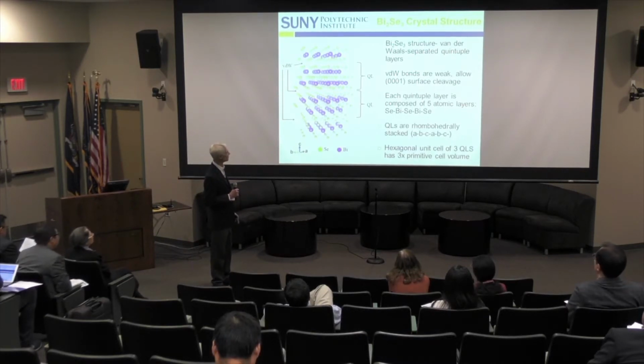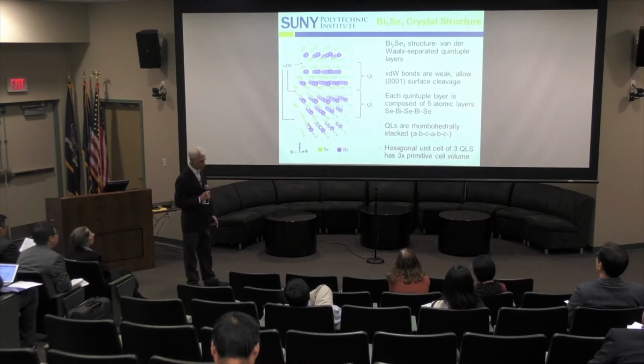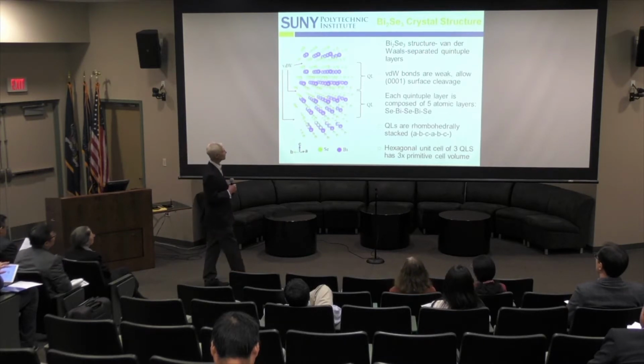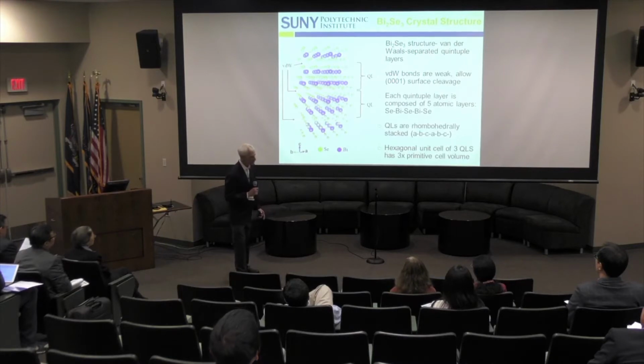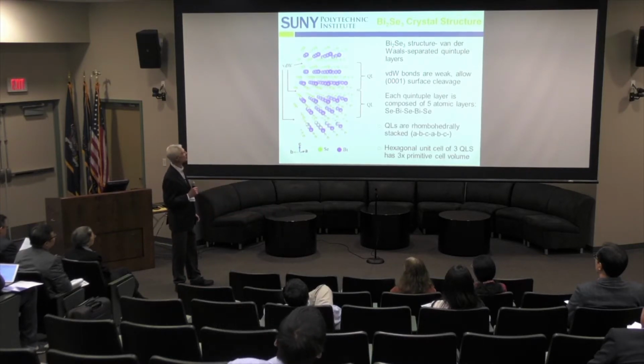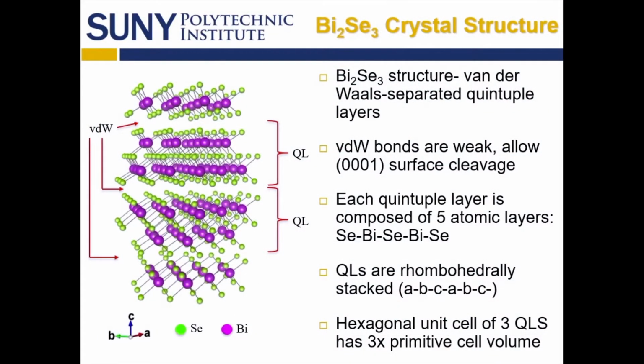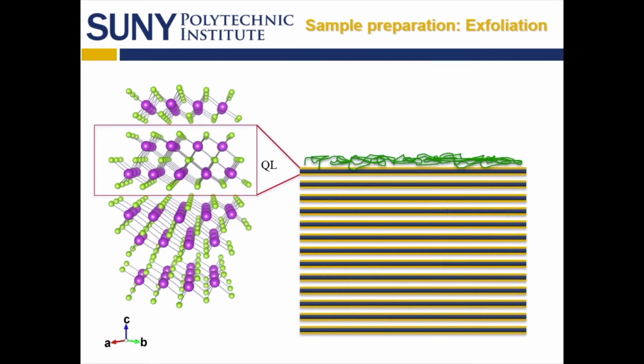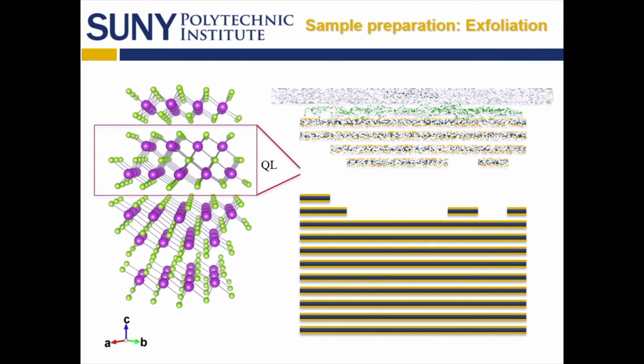is one of these new topological insulators which have very unusual electrical properties. The momentum and spin are locked, and supposedly you can have spin-based transport across one of these materials, and small defects in the surface won't scatter an up spin into a down spin, and so forth. These are quintuple layers, so the yellow balls are selenium, the purple balls are bismuth, and so you have selenium, bismuth, selenium layers. These are quintuple layers. They're van der Waals bonded to each other. And so if you take a piece of Scotch tape, you can exfoliate a new clean surface.